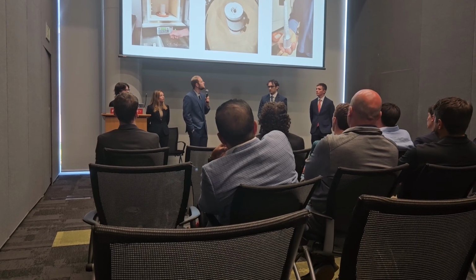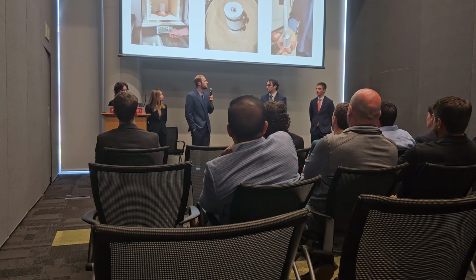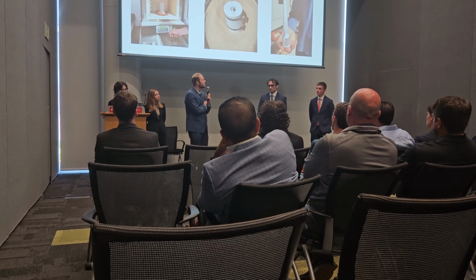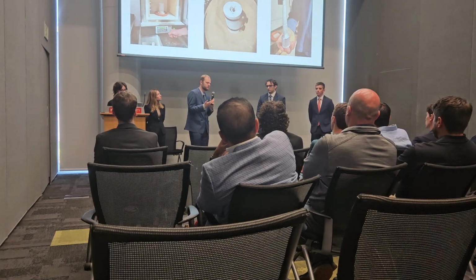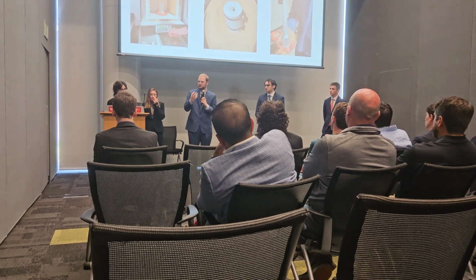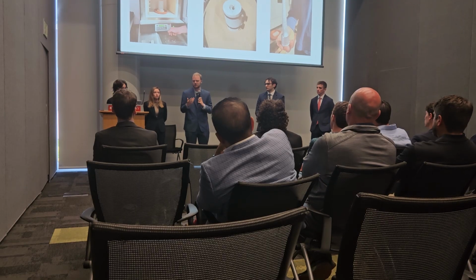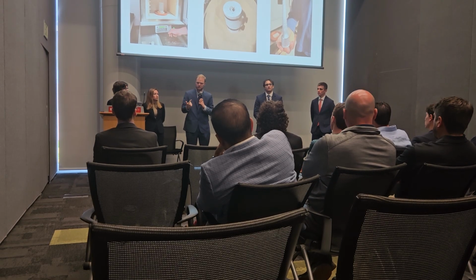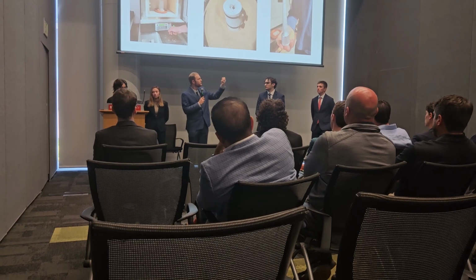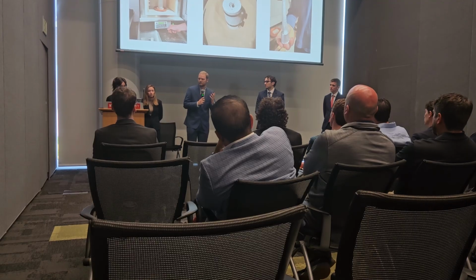The main issue we found with this is that the research paper poured under vacuum at negative 60 kilopascals, and we were not able to replicate this at CAMEL due to the limitations of the furnaces. That caused our fins to not fully form due to the surface tension and also air pockets where those fins are. We had multiple attempts at this where we increased pouring temperature and mold temperature, and also added risers so that air would flow out of where the fins are and material would flow in. In the end, we were not able to successfully get the fins to form.